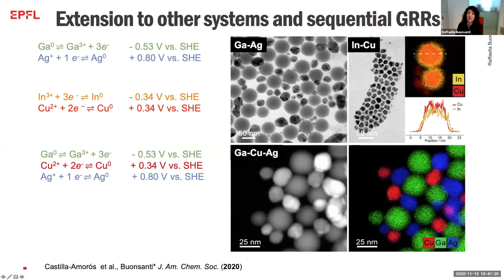And what Laia was able to demonstrate is also that this happens in the case of gallium silver. We can also start to grow copper gallium silver dimers, so we can start to combine more metals together. And now she's exploring also indium. Indium is quite unique because it's less oxophilic than gallium. So we really want to explore the role of this oxide shell. And also indium, we can obtain it as liquid or not, depending on the temperature. So we are going to use indium now as a platform to explore more of this liquid metal.